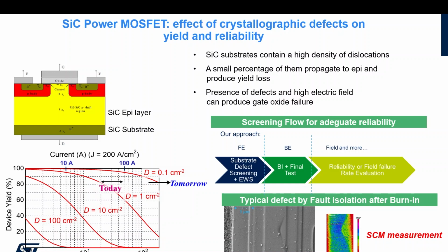So what we do, in order to make sure of this: some defects are killer, some others do not cause electrical failure, but can show up in the reliability. So in order to guarantee the reliability in the final application, we have to do a lot of screening of the initial defects and a lot of burn-in. All the parts that come to the end are submitted to an accelerated test in order to eliminate those parts that would otherwise give early failure in your application. And can you imagine, in a car application, this is a fundamental point.